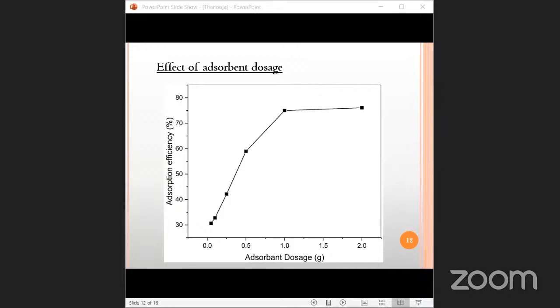This trend can be explained as with the increase in the adsorbent dosage, there is an increase in the surface area and thereby the number of available active sites. But at higher dosages, the nanoparticles agglomerate together, leading to a decrease in the surface area to volume ratio and thereby decreasing the adsorption efficiency.